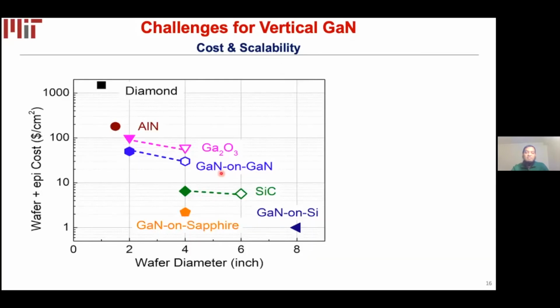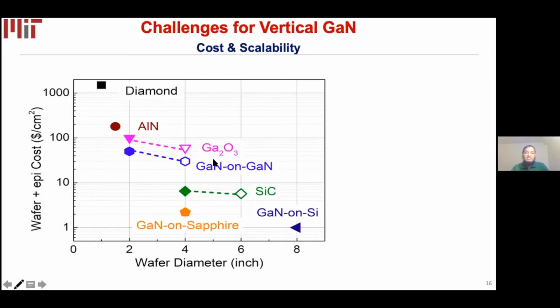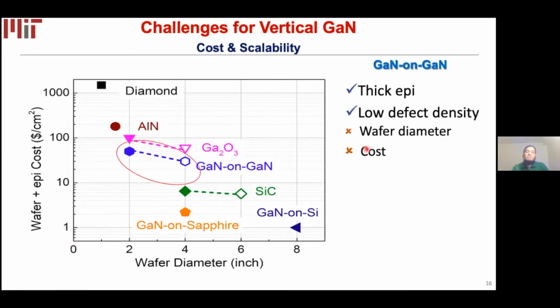And the second most challenging part is the technological scaling of these devices. All these devices were made on, as I said, native gallium nitride, or GaN on GaN substrate. These wafers are excellent because we can grow thick epi with very low defect density, which is important for vertical devices. But the wafer diameter is limited to 2 to 4 inch. And also the cost is significantly higher than any other traditional commercialized technology like silicon wafers.